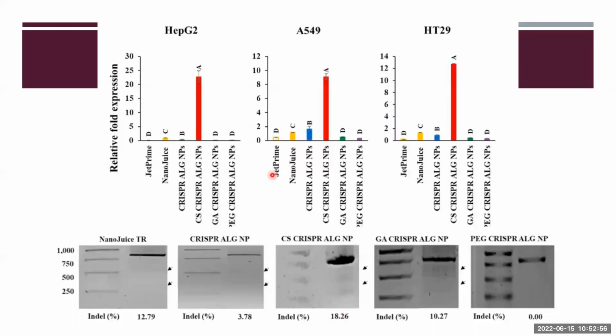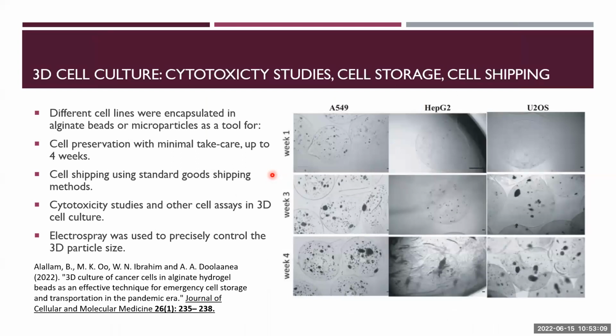So in the previous applications, we encapsulated hydrophobic material. We encapsulated hydrophilic material, and macromolecules like DNA. In another application, we also encapsulated protein, but that has not been published. In the most recent application, we encapsulated cells in these alginate particles. We use both with high voltage and without high voltage. Without high voltage, it's difficult to control the size of the particles, but we use it for another application, which is cell preservation and cell shipping.